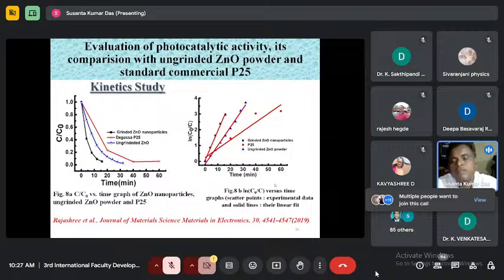This by Beer-Lambert's law, you can know that this is equal to A by A0. A stands for absorbance at any time of exposure, and A0 stands for absorbance of the dye solution at 0 exposure time. Because we are finding the absorbance, their ratio simply gives us the C by C0 ratio. And you can see initially this is 1 and it is gradually decreasing. And you see the black curve represents our grinded zinc oxide nanoparticles, and the Degussa was showing much inferior result than our materials.